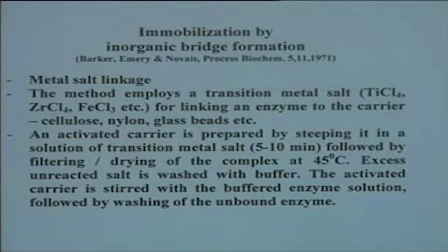So the time of contact is very important, and it is mostly not steeped for more than 5 minutes. If you take a dilute solution, probably you can go higher. It is steeped and followed by filtering and drying of the complex at 45 degrees centigrade, and excess unreacted salt is washed with buffer. The activated carrier is then stirred with the buffered enzyme solution, followed by washing of the unbound enzyme. The method is very simple.